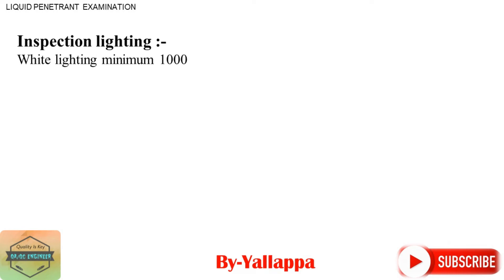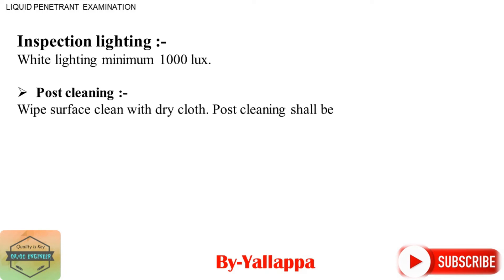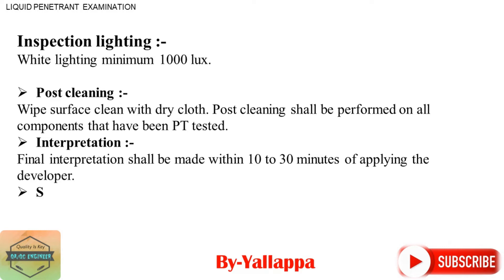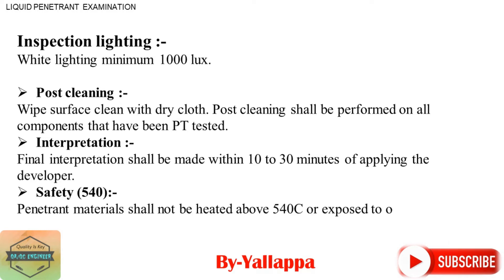Dye Penetrant Inspection Lighting: White light minimum 1,000 lux. Post Cleaning: Wipe surface clean with a dry cloth. Post cleaning shall be performed on all components that have been PT tested. Interpretation: Final interpretation shall be made within 10–30 minutes of applying the developer. Safety: Penetrant materials shall not be heated above 54°C or exposed to open flames.